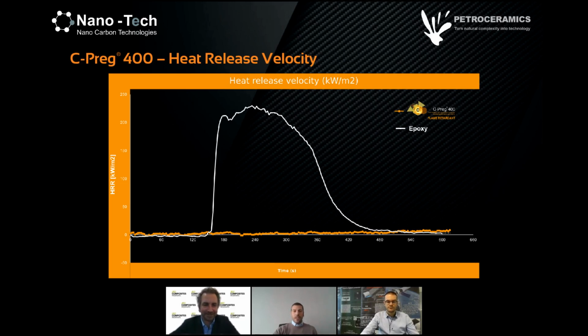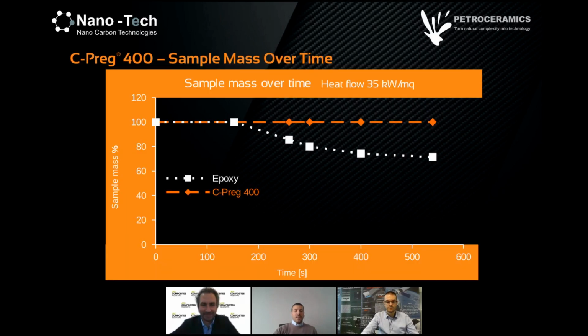Thank you, Benjamin. And this is the chart taken from the same test, the calorimeter test. This shows the time against the sample mass. As you can see, the mass of Cpreg remains close to 100% of the original mass, while after the ignition the epoxy starts to lose mass and goes close to 65–70%. So it basically loses, let's say, all the organic part.